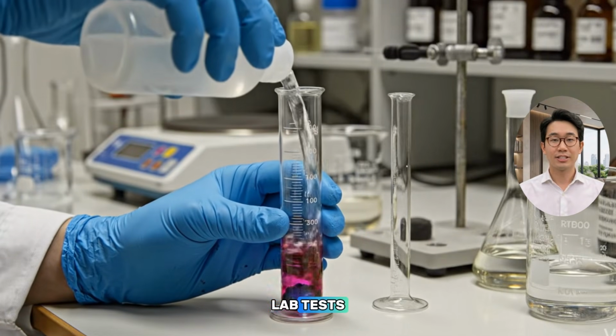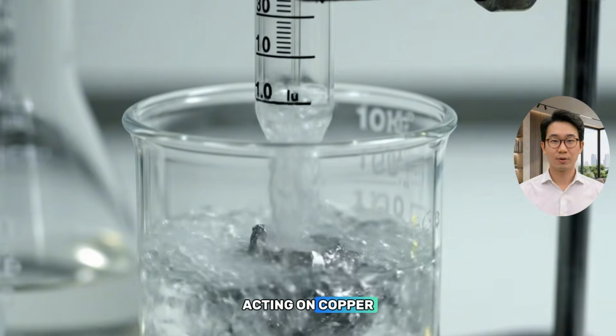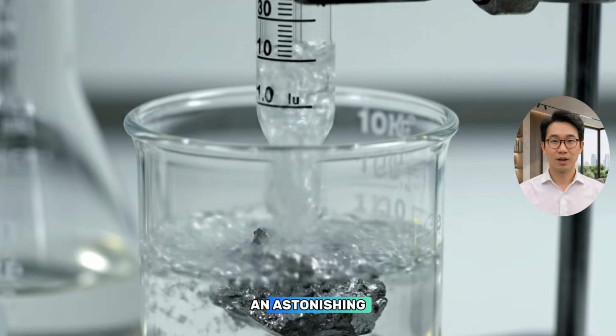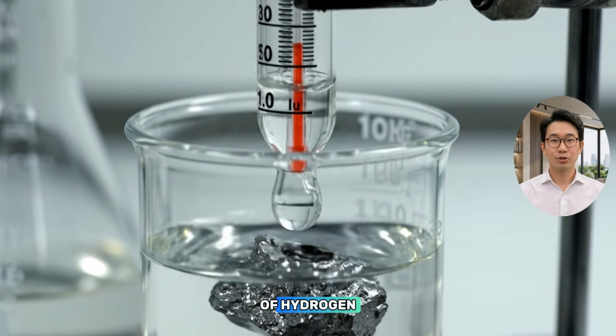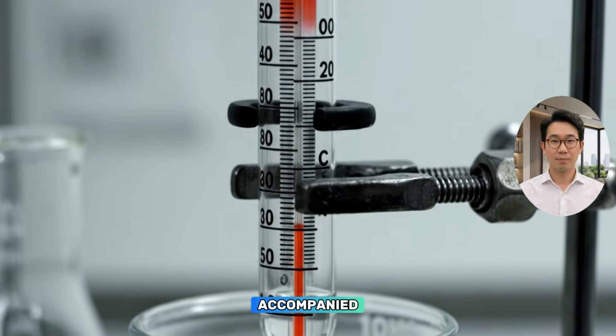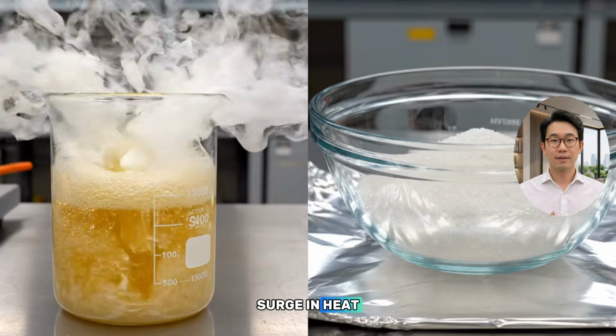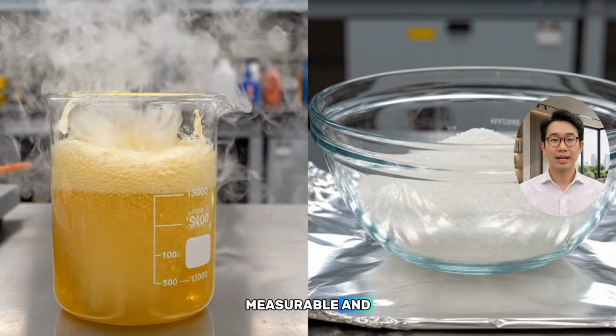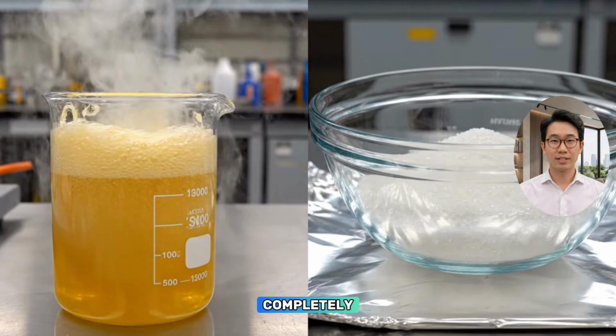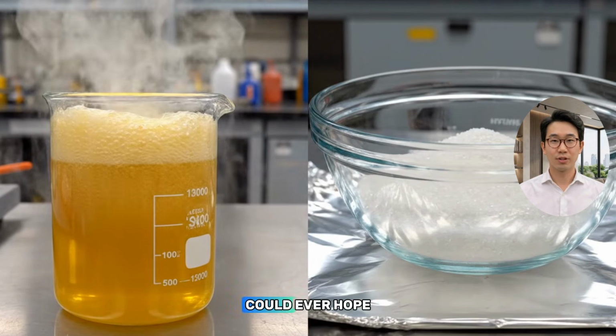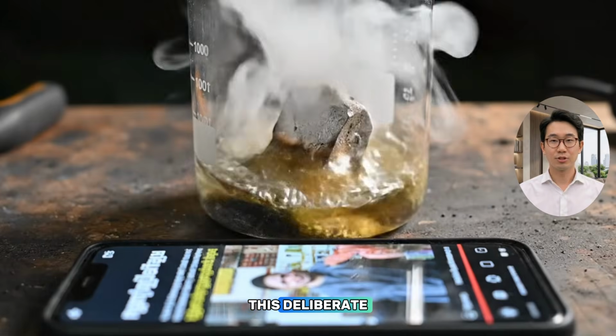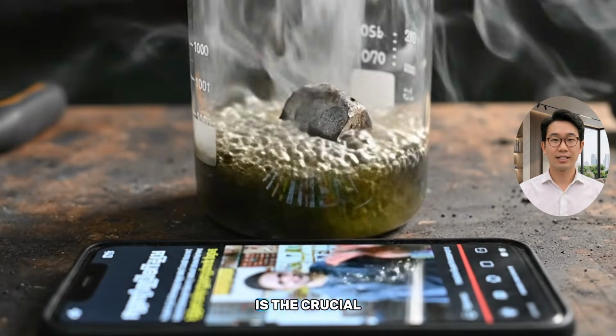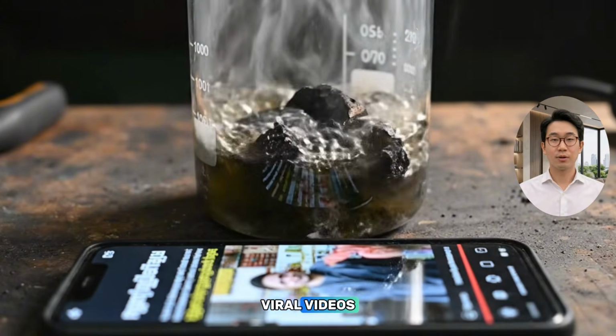In standard lab tests, alkaline solutions acting on copper-activated aluminum can unleash an astonishing 1.8 liters of hydrogen for every gram of metal, accompanied by a massive surge in heat. The results are highly measurable and consistently reproducible, completely blowing away anything plain salt could ever hope to achieve. This deliberate, aggressive chemical unlocking is the crucial step those viral videos leave out.